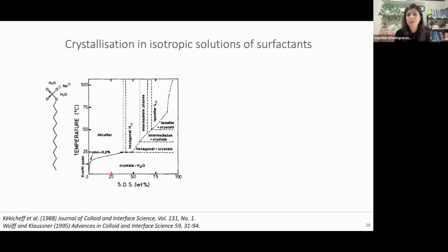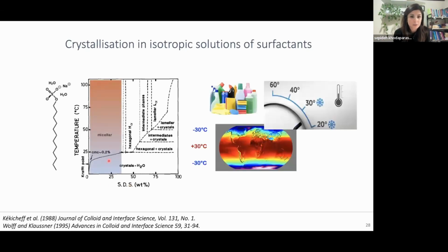And every time you have crystallization, you're consuming the micelles, so you're significantly reducing the cleaning efficiency. I'm going to focus on one single surfactant, sodium dodecyl sulfate, which appears in the majority of the detergents that you're probably using at home. And something special about this one is that we use it a lot. But if you look at this phase diagram, you see that the temperature at which the micellar phase switches to a crystalline phase and you start losing your micelles is actually quite close to the room temperature.